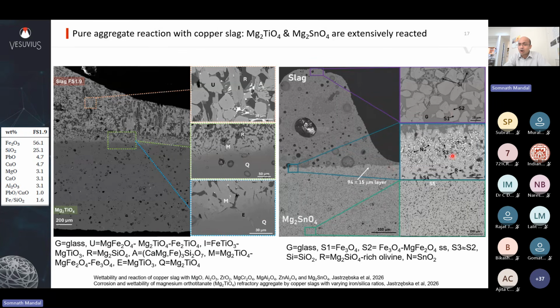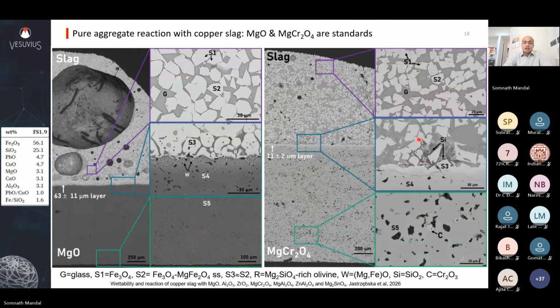Magnesium stannate, you see a similar thing, a lot of reaction and formation of these released tin oxide, these white spots, and a lot of olivine rich in forsterite, and that is bad news because your magnesia is getting dissolved away. However, with the standards, you see that there is almost like a reaction layer formed, which is magnesia-wustite solid solution, this W phase, and then you have a little bit of forsterite close to the refractory interface, but not enough in the slag away from the refractory. So this is an indication that when you're checking the slag away from the refractory and it does not have any new phase, just the phases that are normally present in pure slag, then you know that, okay, it's good news. You have very little corrosion of your refractory. And then you see magnesia-chrome, very little reaction of the refractory, and you know that these are standard products used in the industry.